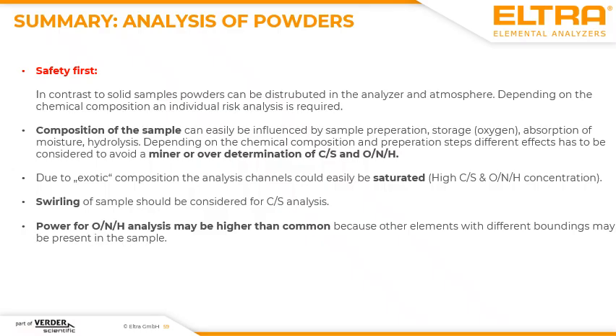At the end, I would like to give you a short summary, because maybe you recognize that some hints for carbon sulfur analysis and oxygen, nitrogen, hydrogen analysis are the same for powders. Most important is when you are getting a new powdered sample and you're not familiar with analyzing these kinds of samples, please make sure that the analysis is safe, especially for samples which contain lead, cobalt, and other toxic ingredients. When you have a powdered sample, the damage for the analyzer and especially for you as a human being could be much more in comparison to a solid sample.